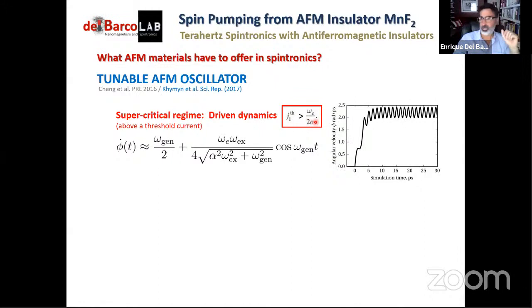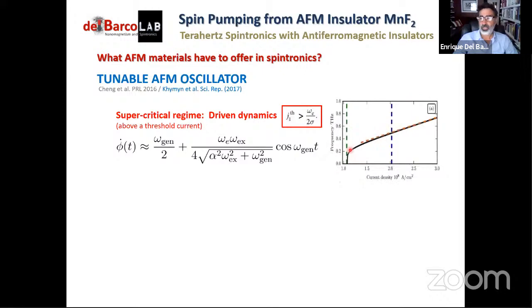So above a threshold current, we are in the supercritical regime, in which the current actually drives the dynamics of the system. So you'll see after some time of application of this spin current, for example, we'll have the system oscillating naturally at a particular frequency. And indeed, it's easy to see that the frequency of oscillation is going to depend almost linearly on the current density flowing through the platinum, the adjacent material.